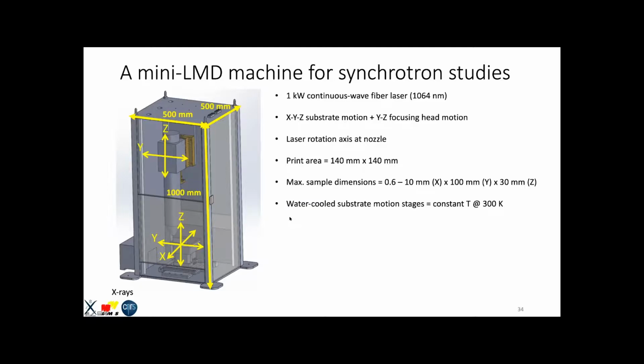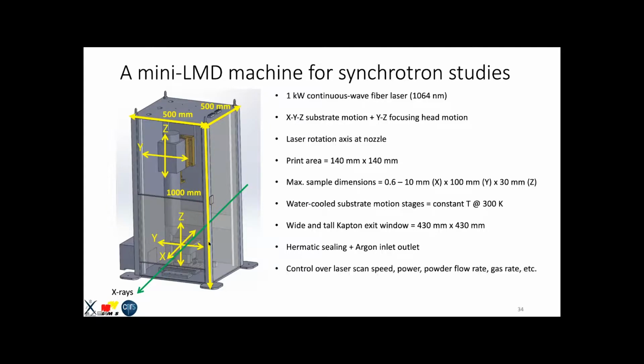Or for X-ray diffraction, we will keep it in this direction, but I'll tell you the advantage later. The max sample dimensions will vary from 0.6 to 10 millimeters in the X direction, which is this direction, 100 millimeters in the Y, and 30 millimeters in the Z direction. So it's pretty large samples. The substrate is water cooled, so we have a constant temperature, which is great for modeling because we can have at least one Dirichlet boundary condition. The X-rays will be coming in from this direction. They will interact with the material, and we have wide and tall Kapton windows at the exit, which allows us to have a large diffraction angle. The thing is hermetically sealed, and there is an argon inlet and outlet so that we can do everything under inert gas, and we have control over almost everything inside.